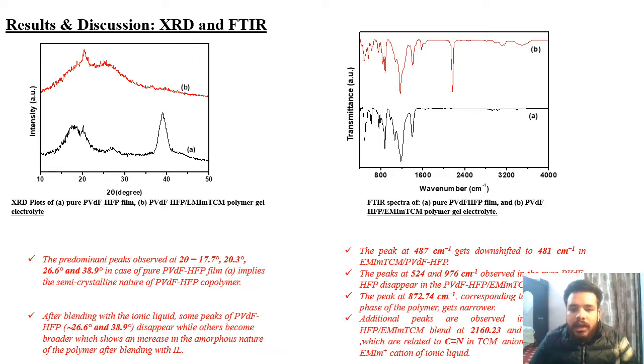On the right side, you can see the FTIR spectra of pure PVDF-HFP film and ionic liquid doped PVDF-HFP polymer gel electrolyte. The black portion is showing the pure PVDF-HFP film, and the red portion is showing the ionic liquid doped PVDF-HFP film. The peak at 487 cm^-1 gets downshifted to 481 cm^-1 when ionic liquid is doped, and the peaks at 524 and 976 cm^-1 observed in PVDF-HFP disappear. The peak at 872.74 cm^-1, which corresponds to the amorphous phase of the polymer, gets narrower when we add ionic liquid.